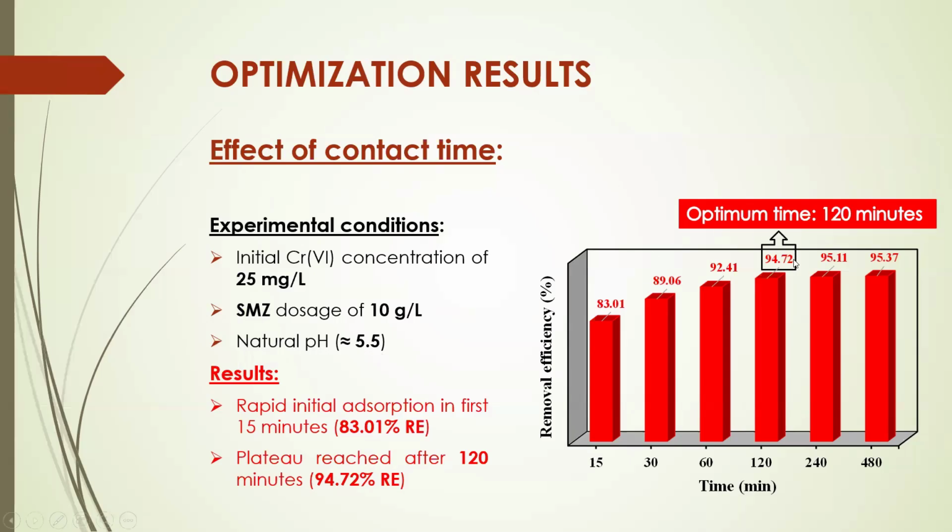Extending the contact time to 120 minutes, we obtained more than 94% removal efficiency. That's an 11-point improvement. At 240 and 480 minutes, we saw essentially no significant additional removal.